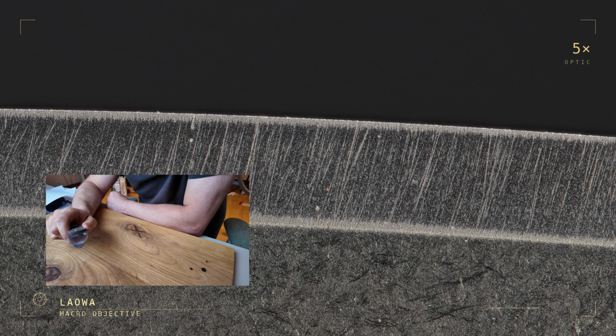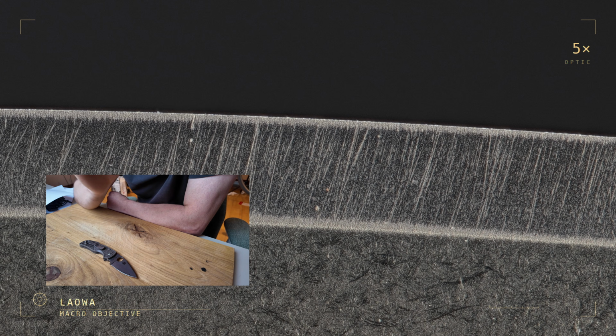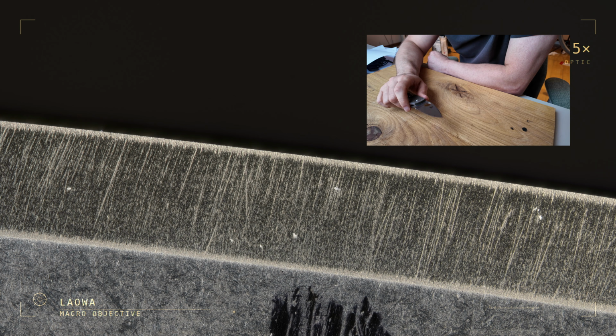All that white stuff is carbides. You can see the concentration at the edge, and that's because I seem to have slightly over-angled when I was stropping freehand. That should actually make the apex slightly stronger. And then finally, this is the business part. This is the part we will actually be doing the cutting with. As you can see, there is no burr to be seen. This is that sharpened edge at 20x magnification, and you can clearly see a huge amount of exposed carbides.